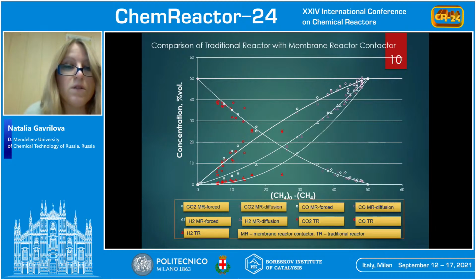The dependence of the change in the concentration of all components of the reaction on the consumption of methane confirms the complete identity of the chemical and transport stages in both modes of the membrane reactor. For all components of the reaction mixture in both modes, the concentrations lie on the same trend lines, as you can see in this figure.